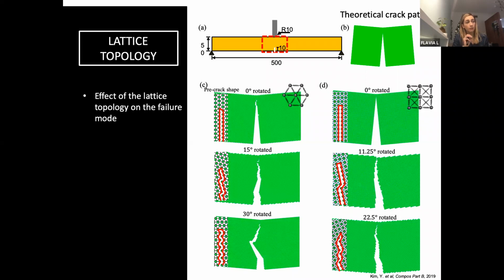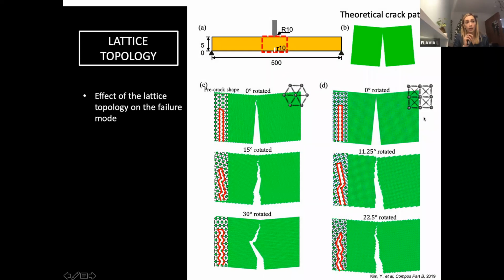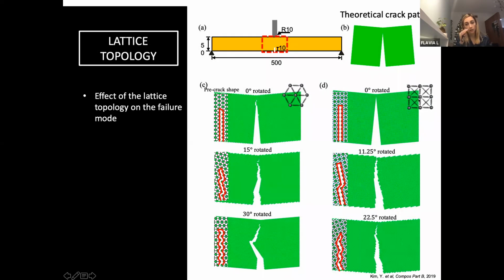What is interesting is that you can actually notice a difference if you have different lattices implemented. If you look at all the images on the left, here we use a triangular lattice spring model, and here on the right we used a square lattice spring model with two different spring constants for the diagonal one and the horizontal or vertical one. And you can see that we have a different failure mode with respect to theoretical prediction, especially if we consider not only the two different lattices, but also the orientation of the lattices. Here it is 0 degrees rotated, here 15 degrees rotated, and then 30 degrees rotated.